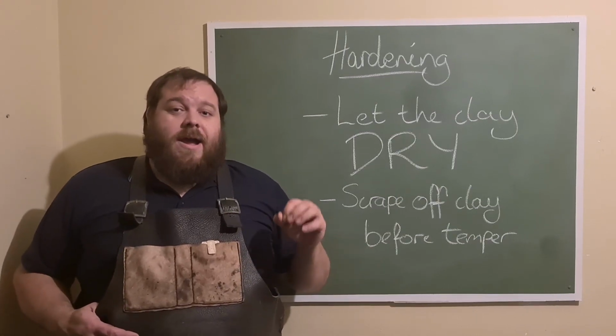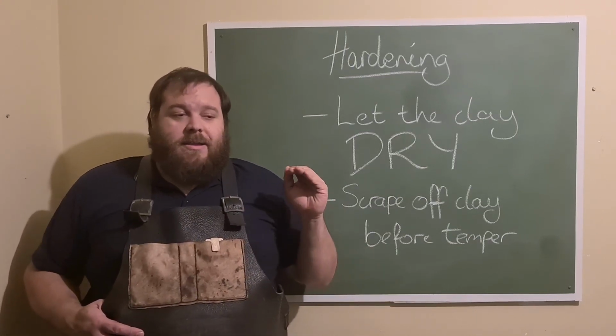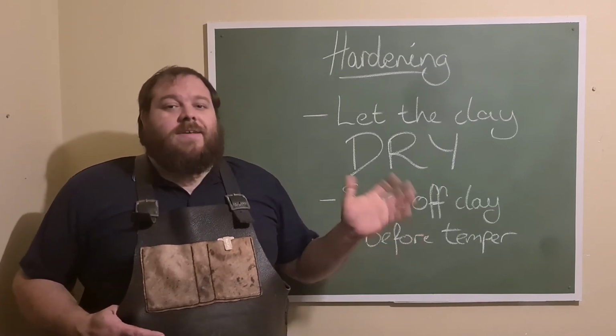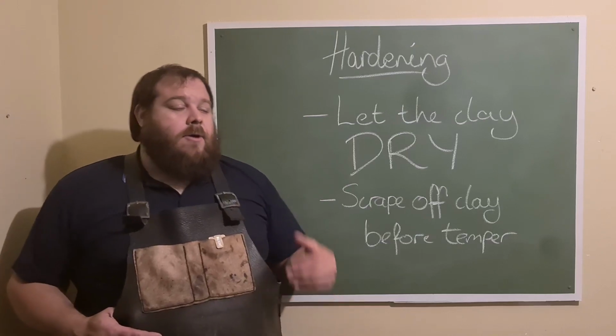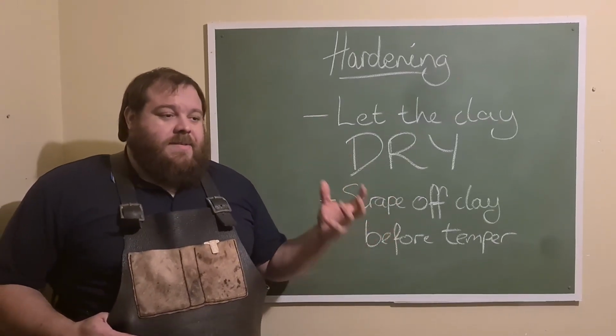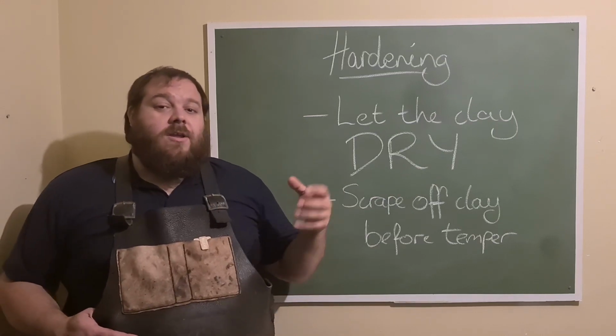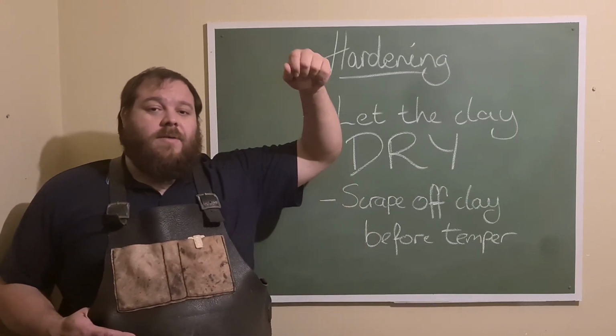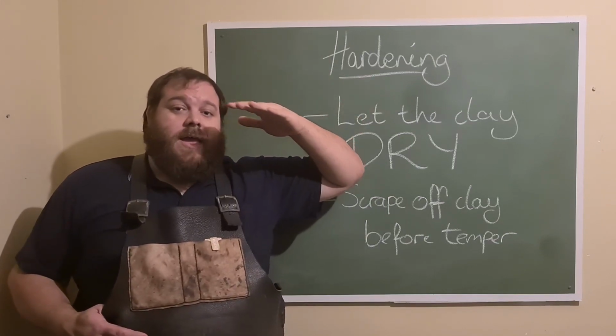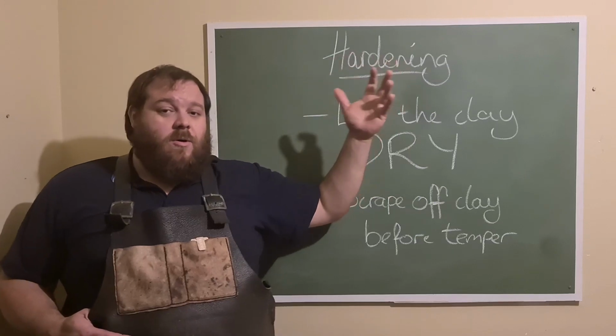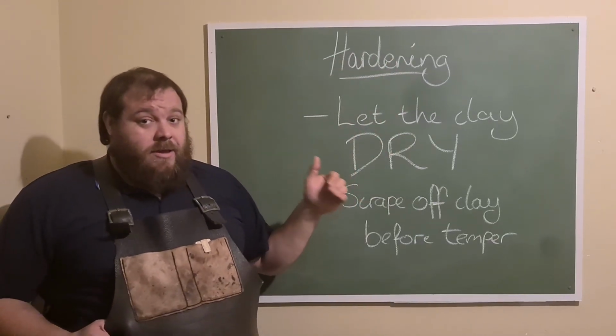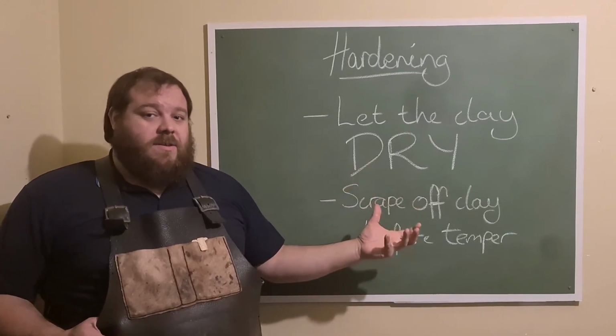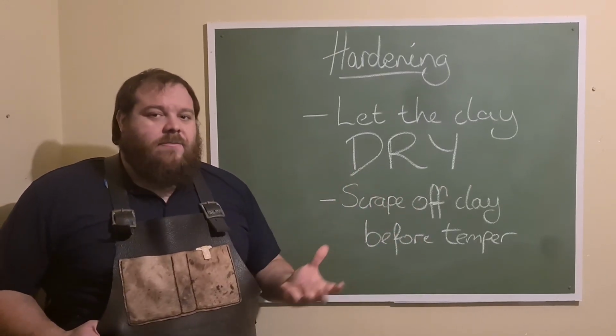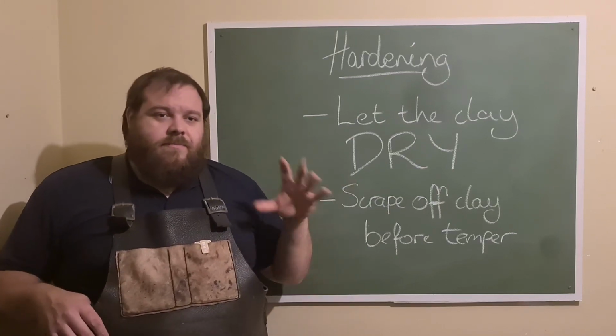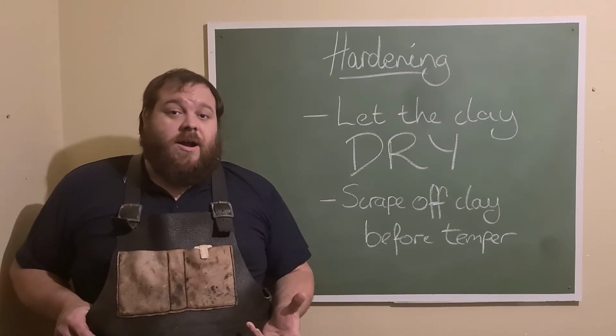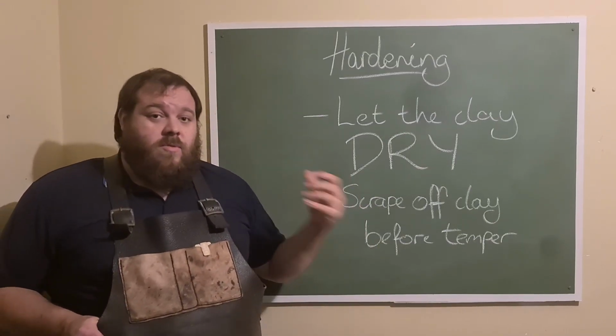It may crack. If it cracks, fill the cracks with more clay. Don't worry about it if it cracks, unless it cracks and falls off, in which case you may have to reapply. Now, I have in the past, in my haste, dried it over the top of the forge. I will either hang it above the forge, or I will place it above the forge if I've got a charcoal forge a long way away, so that it's in the warm air, but it's not anywhere near the fire. That can work. Of course, the faster you dry, the faster you may crack it. So just be careful when drying your clay. But normally the sound rule is to leave it 24 hours to dry. Once it's dried, you're ready to heat treat.